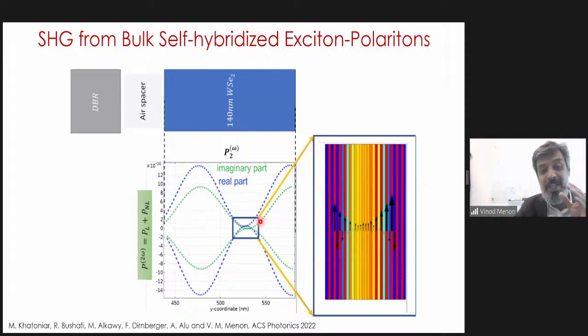But that is coming about because of the way the electromagnetic field is sitting inside the structure. So I'm not saying that I've violated anything that has been written in any of the nonlinear optics textbooks. The only take-home message from this experiment is that you could take a centrosymmetric material and still get nonlinearity if you can design your electromagnetic field appropriately, where you break the symmetry not by the structure itself, but by the way the field is sitting inside the structure. And with these 2D materials, it's easier to do because these layers act almost independently and the polarization created in each layer is different. So that's the take-home message. The textbooks still hold, except you need to worry about how the field is localized inside the structure. And through this, you can actually break some of these rules if needed.